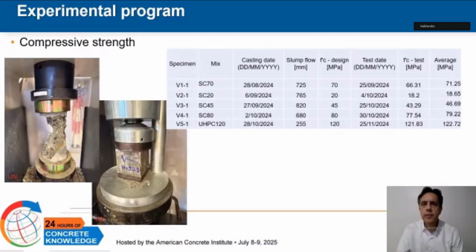This table summarizes the compressive strength results obtained from standard cylinder specimens tested at 28 days for each concrete mix. The target strength, known as design f'c, ranged from 20 megapascals for the lowest strength self-consolidating concrete mix to 120 megapascals for the ultra-high performance concrete mix.